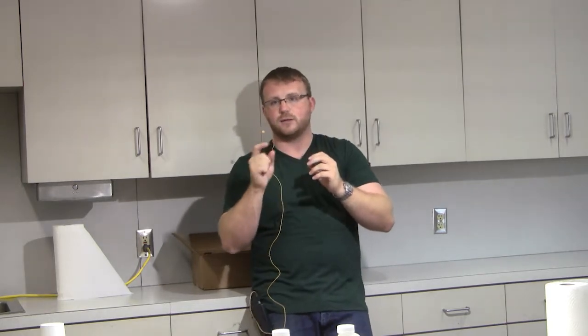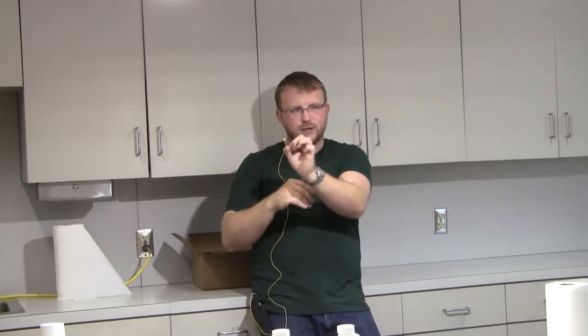And with polyester resin, it's the same thing. You're constantly stirring because you want to get a good blend of the MEKP once it's activated. If you don't stir it well enough, you'll have a soft spot in the blank. If you've ever turned a pen blank that's pretty consistent except for one nickel-sized spot, with two little ends that are real soft but everything else is great, it's because they just didn't stir it enough.